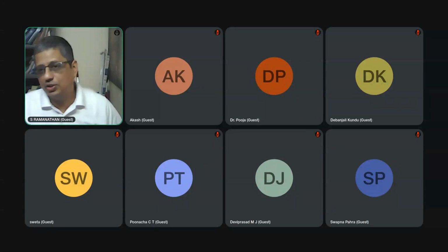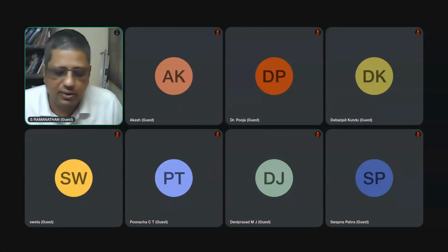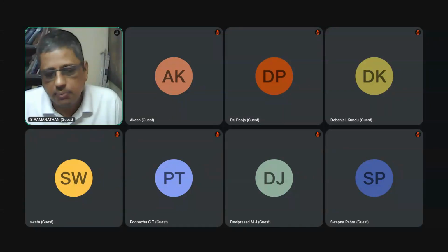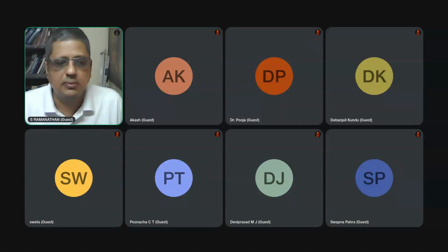Why should the area of the counter electrode match? No, in fact, it should be larger. Ideally the area of the counter electrode should be larger than the area of the working electrode. Imagine you are applying plus 1 volt to the working electrode versus the reference electrode. The plus 1 volt to the working electrode means the potentiostat has to apply negative volt to the counter electrode to give all the electrons into this. How much voltage should it give? All the current taken by the working electrode should be pushed through the counter electrode. That is all the requirement.